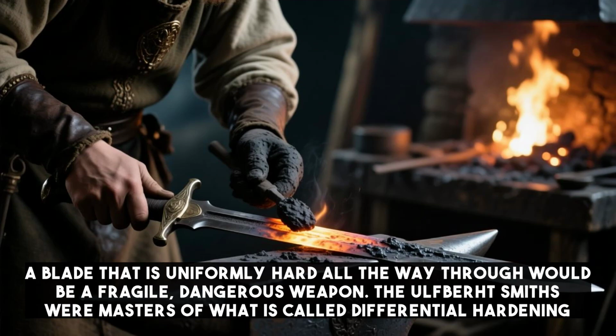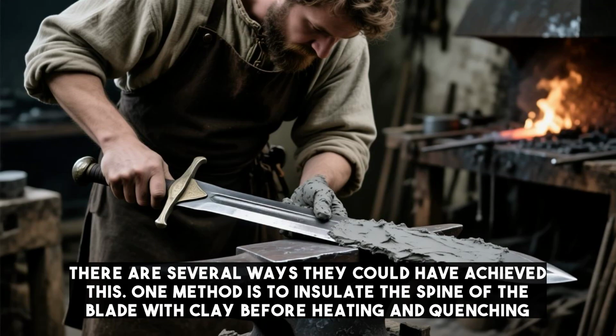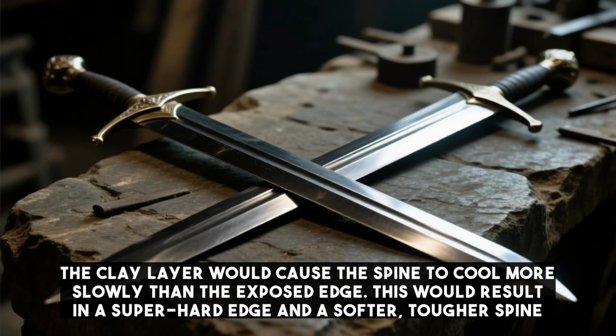The Ulfberht smiths were masters of what is called differential hardening. There are several ways they could have achieved this. One method is to insulate the spine of the blade with clay before heating and quenching. The clay layer would cause the spine to cool more slowly than the exposed edge. This would result in a super hard edge and a softer, tougher spine.